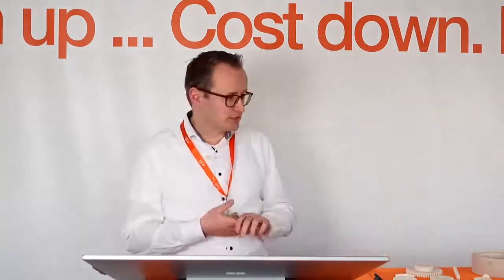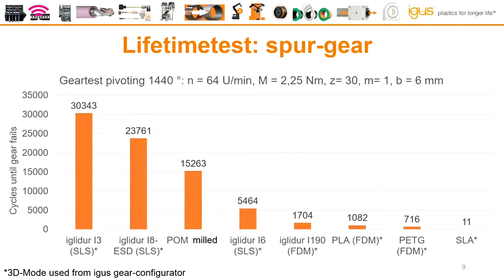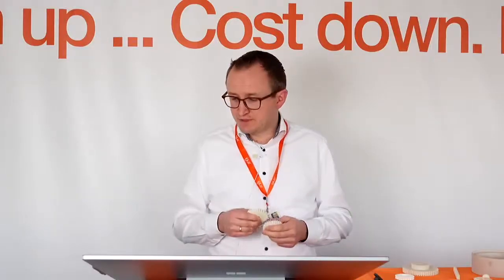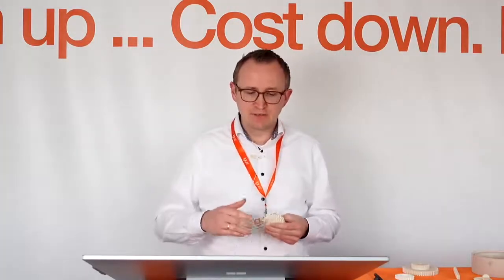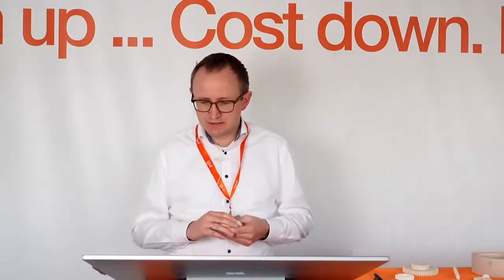And that's another test result we did for such regular gears, as you know them from regular gearboxes. And in this test, you see a big difference between the different printing methods. So the FDM filament printed gears are not holding as long as the laser sintering gears, as for example iglidur i3, which had the highest lifetime for such regular gears. That's why we're also using iglidur i3 for such regular gears all the time. And you see we even have here a 2 times better lifetime compared to the regular POM milled gear. And that's another big advantage you have here, that you can even reach a higher lifetime than with regular machined gears.